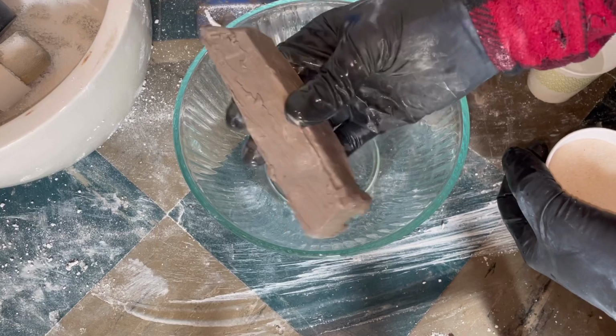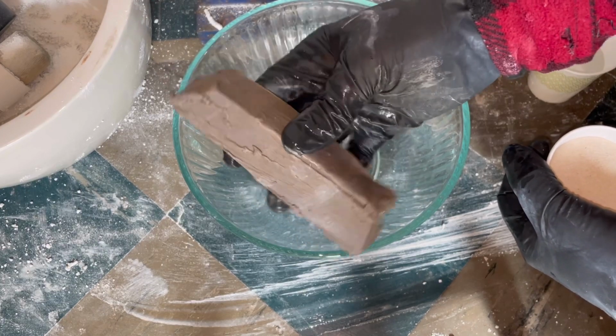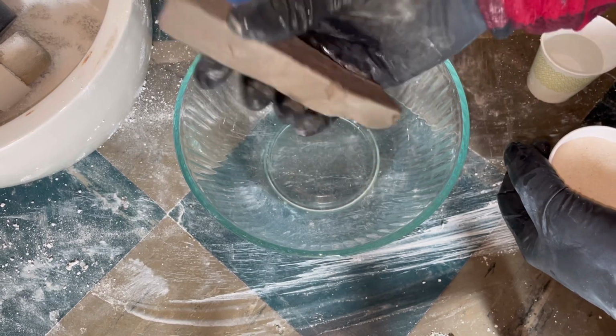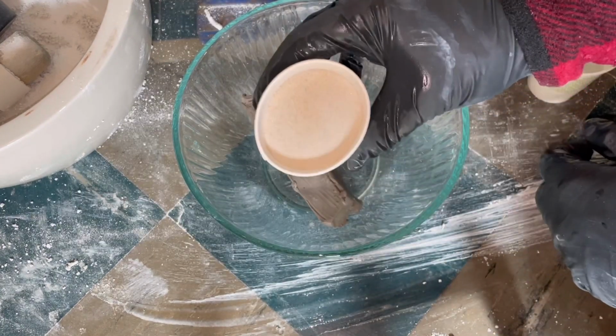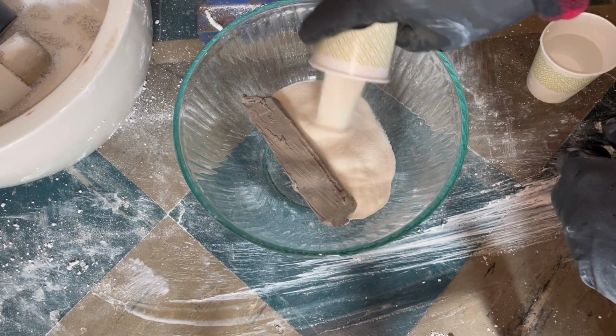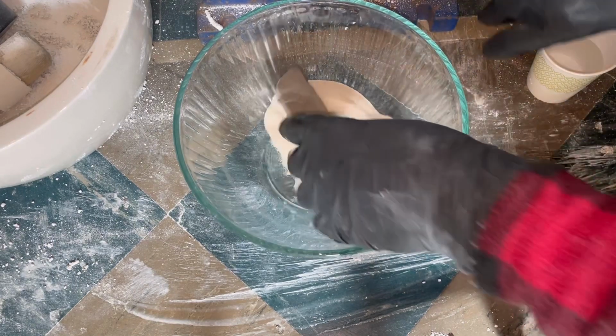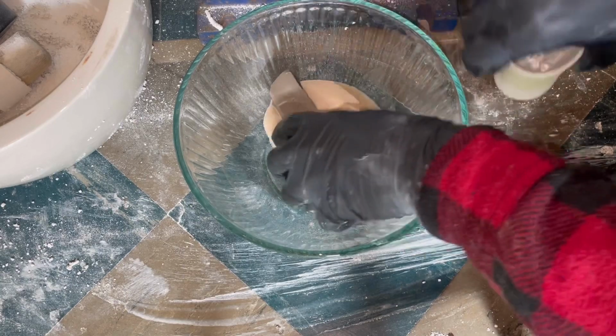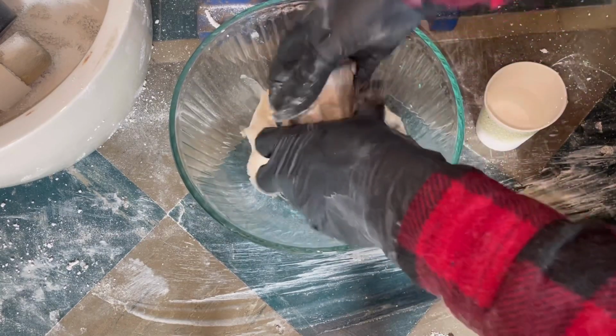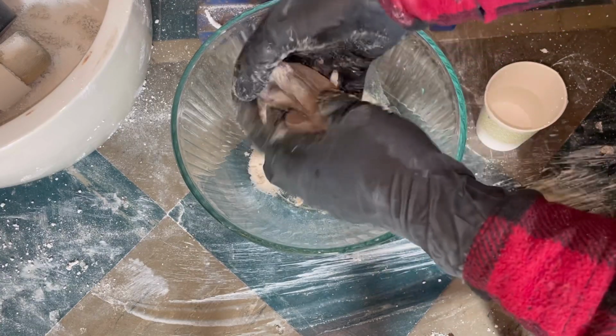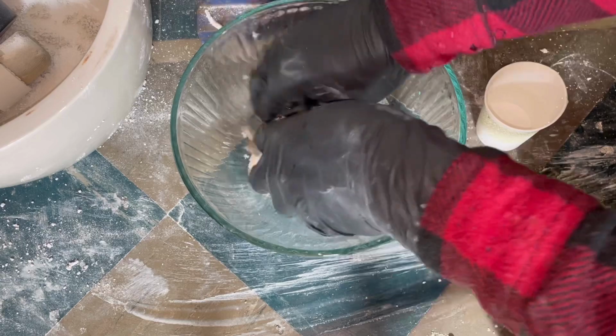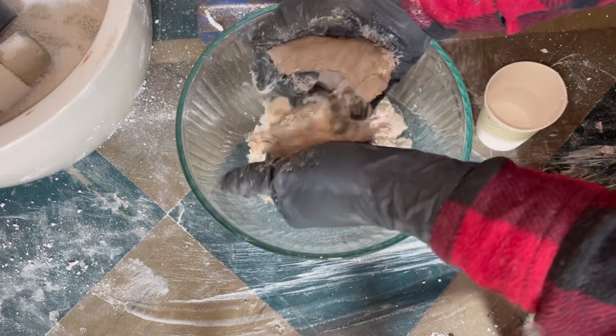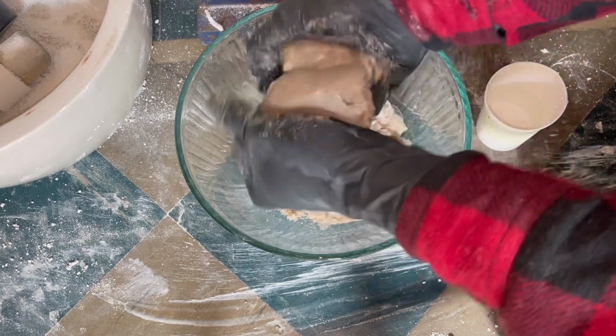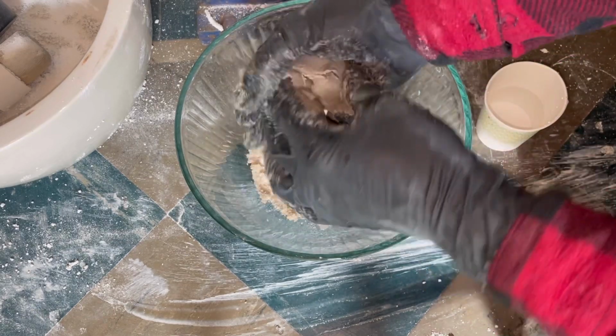Now for the crucibles, I'm going to use a mixture of ordinary pottery clay, just some low-fire clay that I bought from the craft store, and a roughly equal volume of fine silica sand. Okay, add a little bit of water and get these mixed together. The sand, silica doesn't expand as much as the clay does when it's heated, and so it helps with thermal shock.